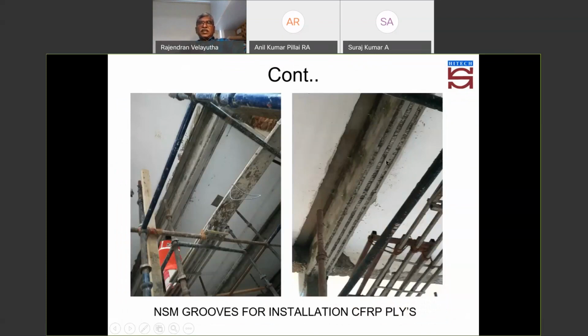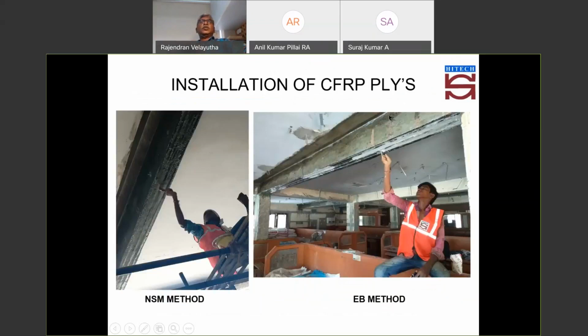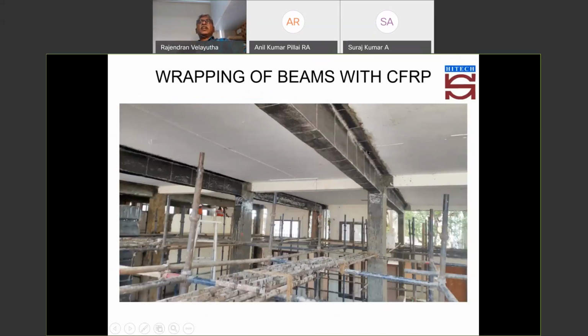So we were not able to go with an NSM. So we went with the CFRP strips onto the bottom of the beam, and then applied epoxy glue in this bedding area so that the entire surface will be uniform, which will reduce issues with your CFRP wrapping. As I said, first is the strip, and then applying epoxy putty in between the gaps of the strip. After that, you have a carbon fiber sheet wrapped in the shear reinforcement direction. One is that it will not allow the debonding of the strip,